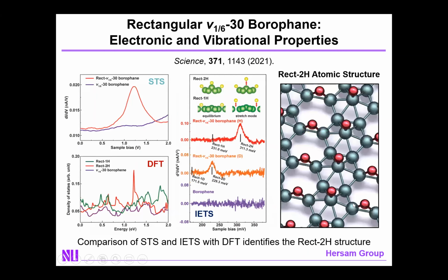And so we did this with two different spectroscopic methods. The first is scanning tunneling spectroscopy, which gives us the electronic density of states. We see a very strong peak at about 1.2 electron volts. And in density functional theory, you see that the rectangular 2H structure also has a peak at that energy. But perhaps even more compellingly, we can look at the inelastic electron tunneling spectroscopy, this is the vibrational structure. And we see that the vibrational spectrum shows clear agreement with the rectangular 2H structure and not with the rectangular 1H structure. And to further verify that, we can deuterate the surface, and we find that this vibrational mode shifts in a very predictable manner, as you'd expect from traditional vibrational spectroscopy. And as a result, we can conclude that the rectangular 2H structure is that which we have achieved.